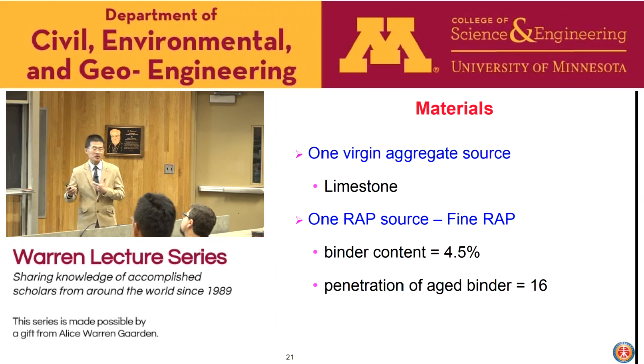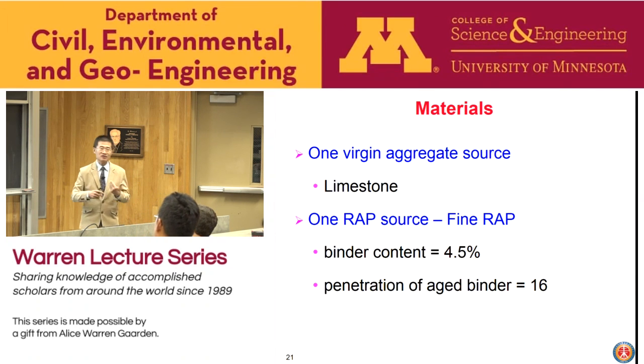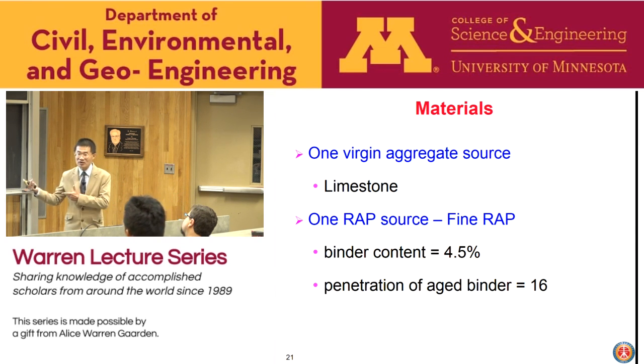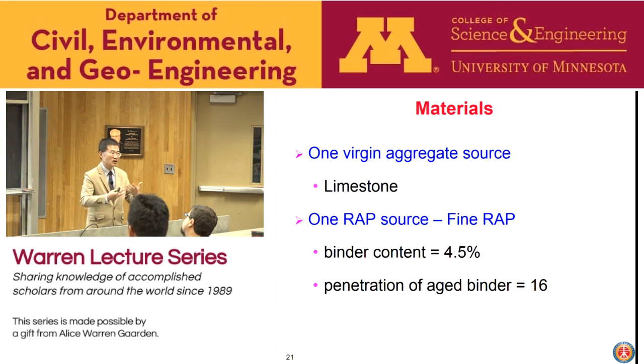So the experimental design in our studies includes only one virgin aggregate, which is limestone, and one RAP source, as I mentioned, which is the fine RAP material. The fine RAP material usually had greater asphalt content than the coarse one. That's why we use it, because we want to extract more of the valuable binder content. Both binder content and the penetration value met the standards I mentioned previously. So that's why we use this type of RAP here in our study.